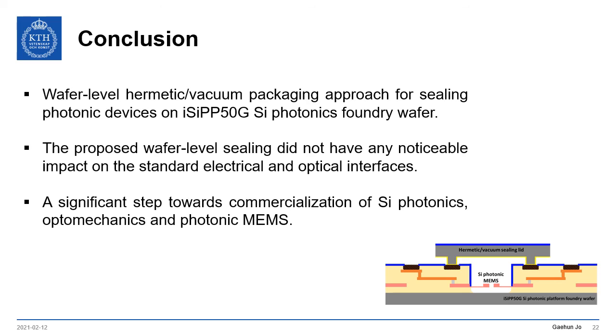To conclude, we present a wafer-level vacuum packaging approach for sealing photonic devices on the ISIPP50G silicon photonic foundry wafer. The proposed wafer-level sealing did not have any noticeable impact on the standard electrical and optical interfaces, and we did not observe a drop in optical transmission for devices underneath the sealing caps. We believe that our approach for wafer-level vacuum packaging is a significant step toward commercialization of silicon photonics, optomechanics, and photonic MEMS.